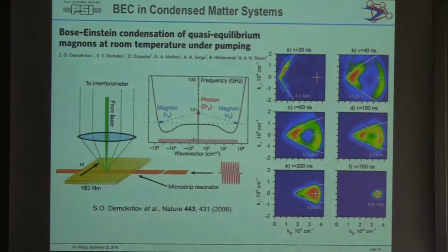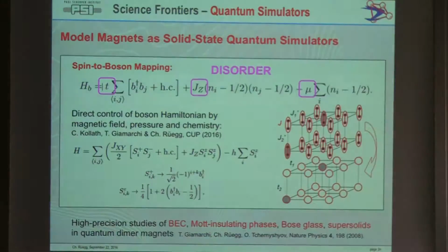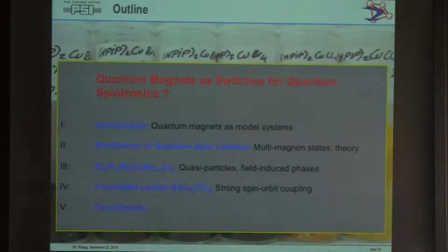So, yeah. Okay, so now the tuning you can have, of course, we often say the cold atoms are very nicely tunable. That's certainly true, but actually these bulk systems also have quite some chemical flexibility. I have done quite some work under pressure where you can control the different exchange parameters as well. So there's actually very powerful ways to systematically control the Hamiltonians in such systems as well. And nobody has a problem to apply magnetic fields to 15 whatever Tesla these days, no problem.